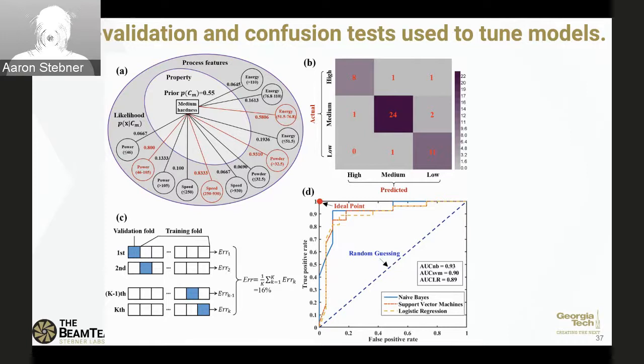And then we also used confusion matrix, so true positive versus true negative, false positive versus false negative comparisons to evaluate which algorithms were the best performers and to optimize the parameters in the algorithms. And then once we did, the bottom right there is what we call a receiver operating characteristic. And that's what we use to decide which algorithm was performing better than the others. In this particular case, all three are performing almost identically. There's within statistical variation, that fraction that you see there, you can almost think of as a percentage of how well one's doing versus the other. So if it was perfect, that number would be 1 or 100%.